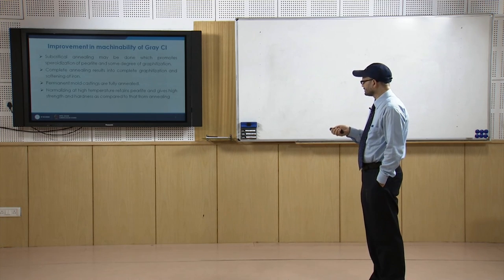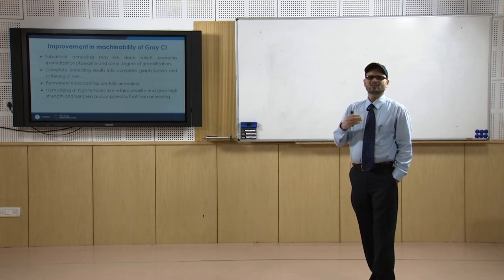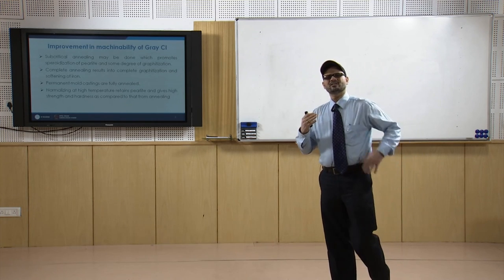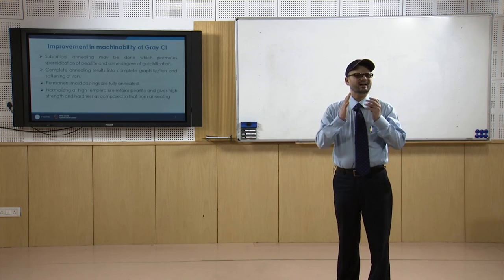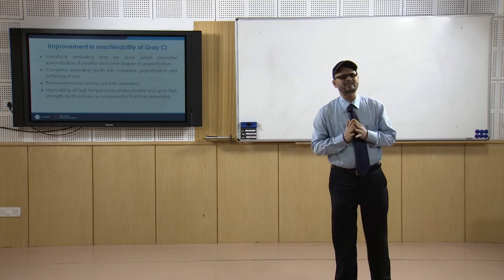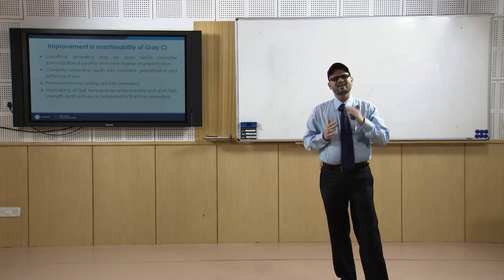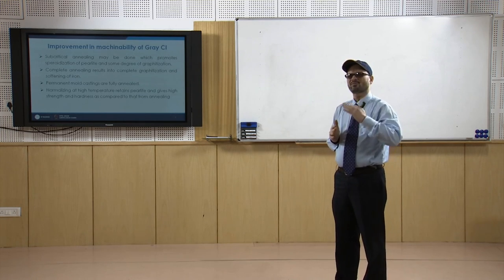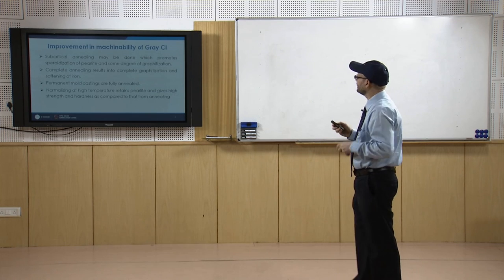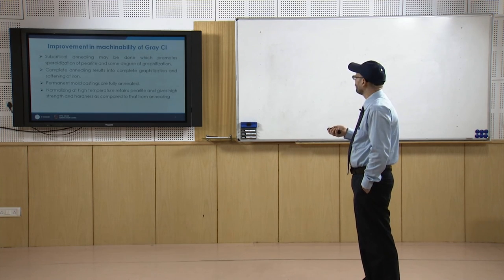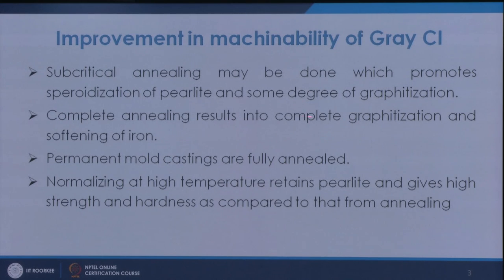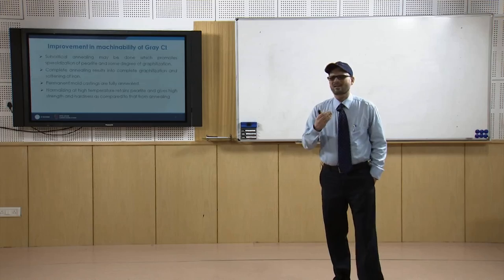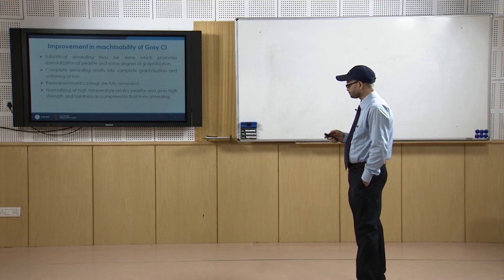Permanent mold castings are normally fully annealed, because in permanent mold castings the heat transfer rate is normally higher than in the case of sand molds. So, here you need to go for full annealing so that complete graphitization takes place and the grey cast iron becomes softer.